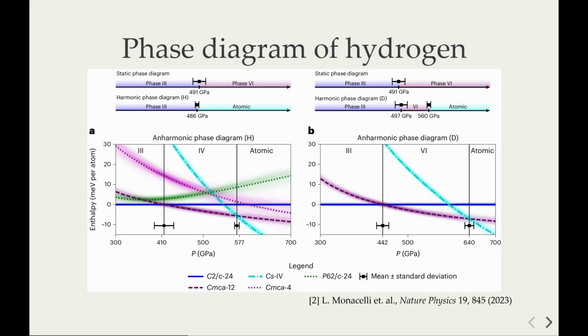If we add phonons in harmonic theory, everything changes completely, and this phase 6 disappears from the phase diagram, and we directly pass from phase 3 to the atomic phase at a pressure which is very high, so half a terapascal mostly, but reachable from an experimental point of view.